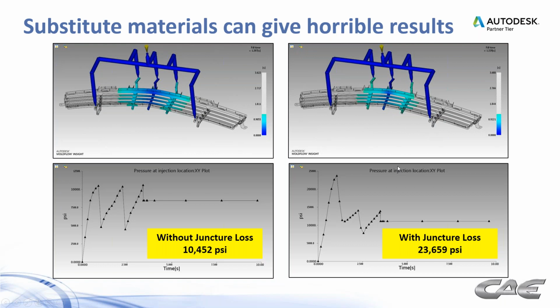Remember, the pressure increases exponentially as you try to reduce wall thickness. So if you're simulating materials that are not well characterized and you're trying to make a decision on whether or not you can mold this thin wall part, you better be very careful with how you substitute materials. Make sure you have good, well characterized materials. And then with the buckling situation as well, these pressures matter when it comes to predicting shrinkage. If you predict pressures well, you predict shrinkage well. If you predict shrinkage well, you predict warpage well. If you predict warpage well, then you're going to detect buckling from time to time, and you want to make sure you got that answer right.